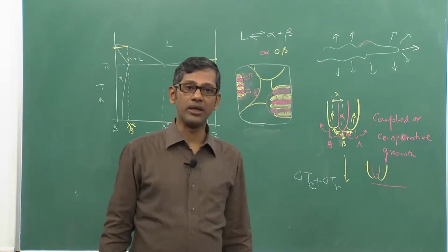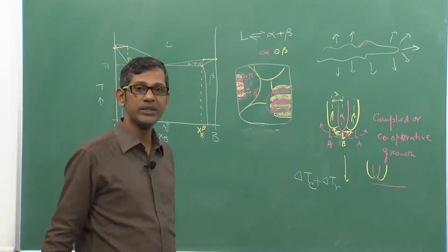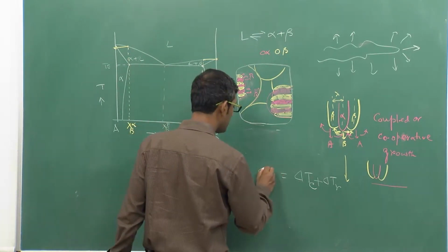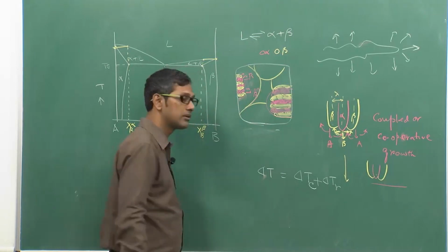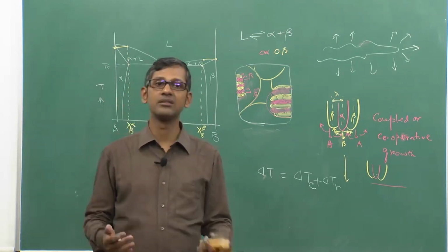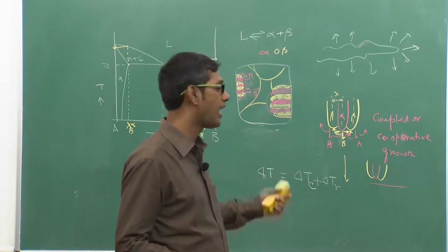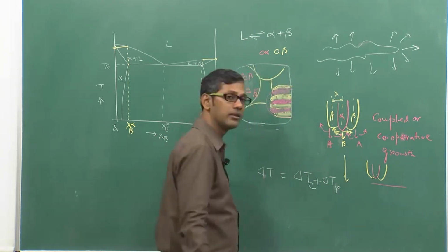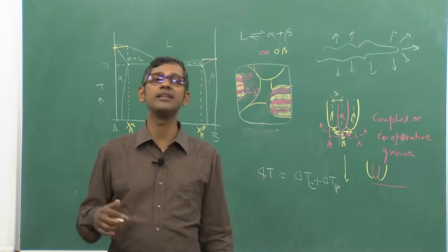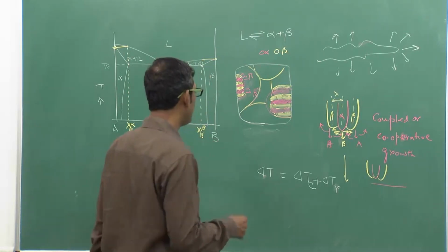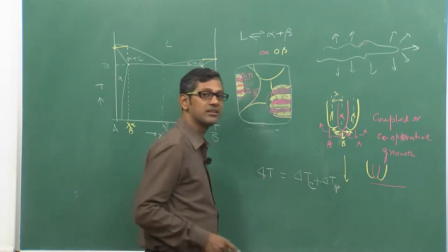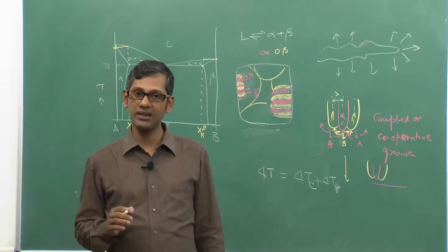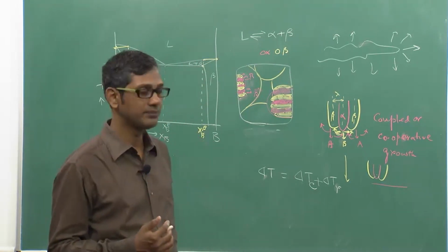So the total undercooling required for eutectic growth is equal to the undercooling because of the curvature, where I have given r, as we always write r because these are curved, so there is a radius of curvature, plus the compositional aspect, delta Tc. These two need to be calculated separately, and only then can we develop a model.